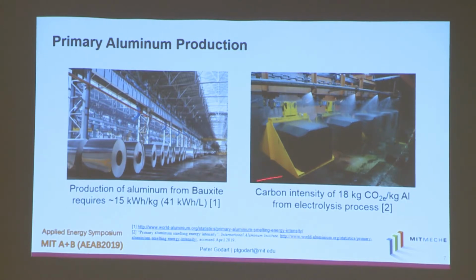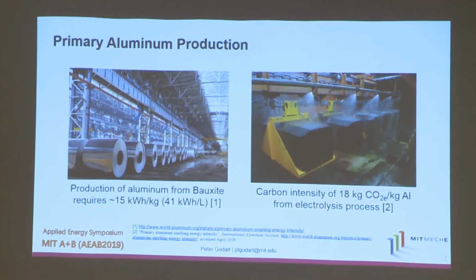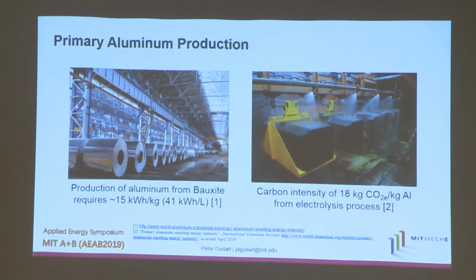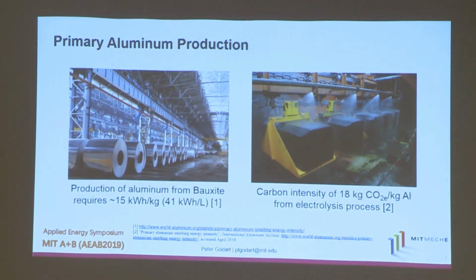And the other issue that compounds this is that the current process most commonly used for removing that oxygen is an electrolysis process that uses a graphite anode to essentially pull those oxygens off, combine them with carbon, and then release carbon dioxide. So this is not a green process either. And people are developing inert anodes for this process, but they're not at full-scale production yet. And I think we are definitely moving in the direction where we could use aluminum as a primary fuel, but we're not there yet. And that's not what I'm advocating here that we do.